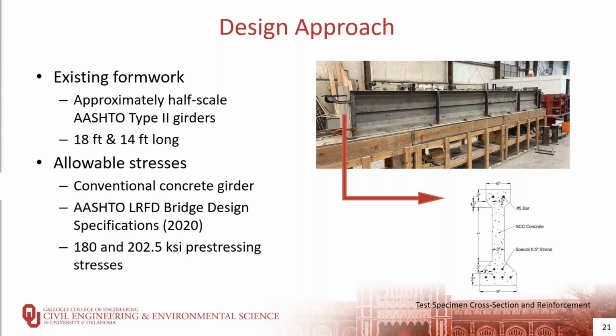The girder specimens were designed to utilize the existing formwork that we have at OU and stay within the constraints of the OU pre-stressing bed, and to obtain the required stress state to match the previous work done by Choate. The length of the hybrid girders was chosen to be 18 feet to match the existing formwork, and in the figures on the right, you can see the existing formwork that was used and the cross-section of that formwork.